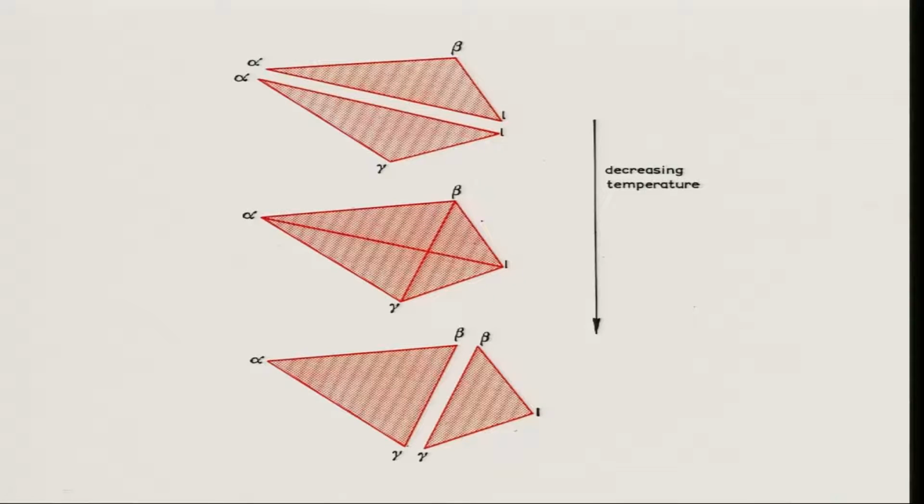Now, that means we form these 2 3-phase equilibria among alpha, beta, liquid and gamma, which descends down to the 4-phase plane. The 4-phase plane is the plane shown at the center, and then the 4-phase equilibrium reaction happens: liquid plus alpha going to beta plus gamma.